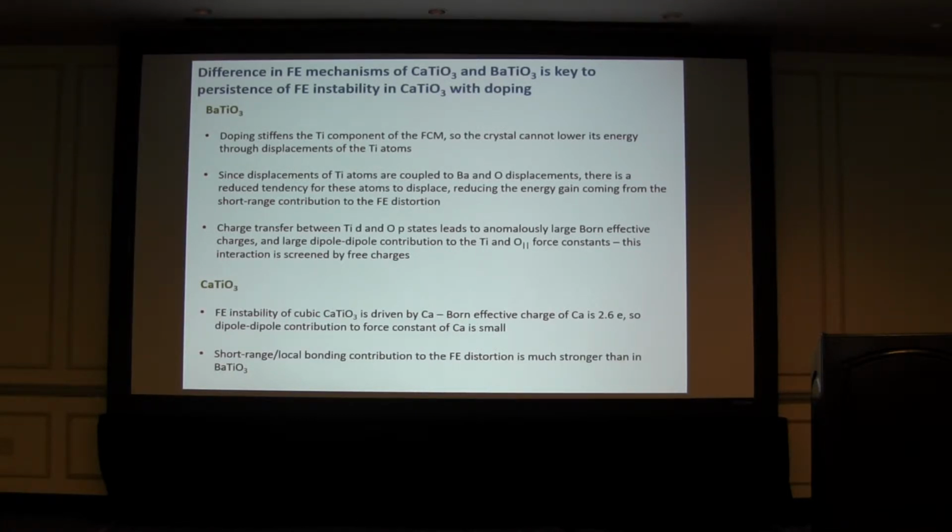So basically you have a small calcium cation that's sitting on this large 12-coordinate site, rattling around, and by undergoing a polar distortion, it can optimize its bonding environment a little bit. Not as much as with octahedral rotation distortions, so they win out in the end, but the polar distortion does help.